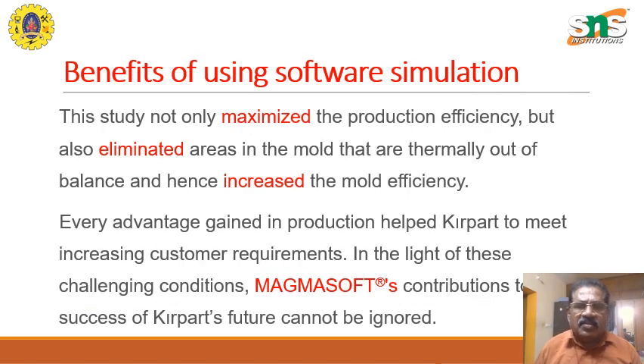The benefits of using software simulation not only maximize the production efficiency but also eliminate the areas in the mold that are thermally out of balance, and hence increase the mold efficiency. The defects can be found out initially, such as trapped air pockets or porosity or the hot spots, etc. All these can be found out in the simulation itself. Every advantage gained in the production helped the company to meet the increased customer requirements. And in light of these challenging conditions, Magmasoft's contribution to the success of Kırpart's future cannot be ignored. It is one advantage of the software that it contributes to the production and the reduction of the defects.